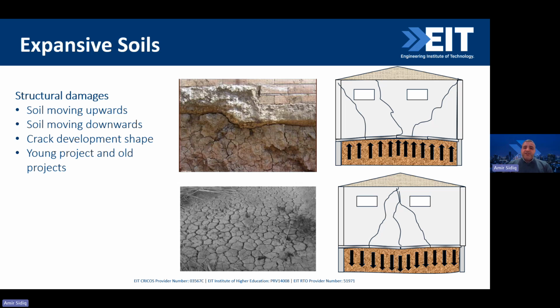Now, at this stage, it does not necessarily mean that if we have swelling occurring, the structure will basically move upward. The swelling is occurring, however the structure is actually sinking because the strength is reducing. And in that case, we have cracks happening. During the initial stages of this swelling, the cracks go from the center upward to the corners. During the shrinkage or the drying, because the structure is sinking, there are two different opposite mechanisms.